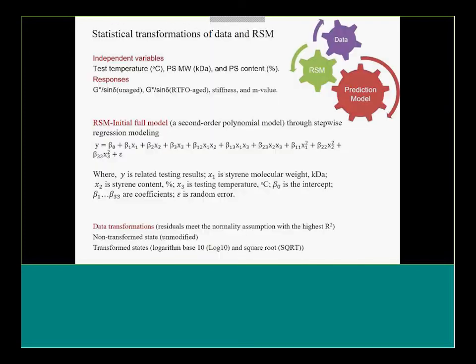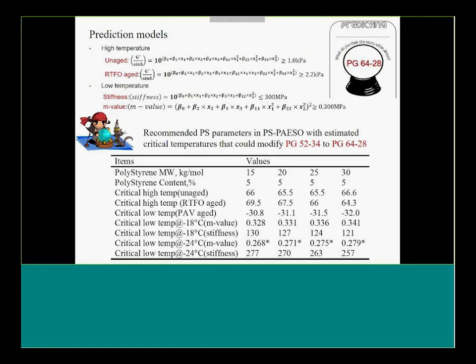Okay, and that we can then use these models to say, all right, if we're going to do a formulation and modify an asphalt, what's the molecular weight of the styrene, which then drives the molecular weight of our PAESO, and have to have matching corresponding molecular weights that marry well together. And then we have to understand what the polystyrene content is, and therefore we know the content of the PAESO. Okay? And so we go through this exercise, and we take a Flint Hills 52 minus 34, and we say, what's it going to take to make this a 64 minus 28? And this is just some of the data from different amounts here.